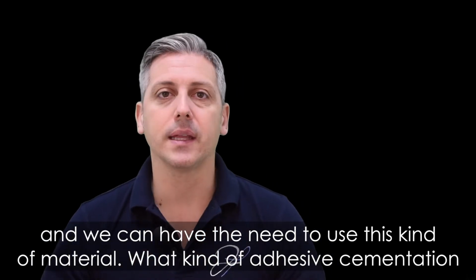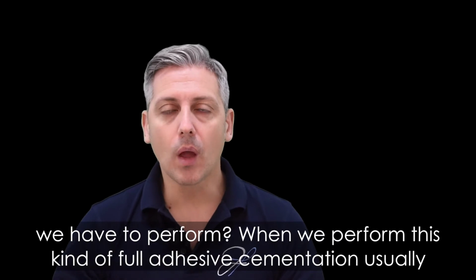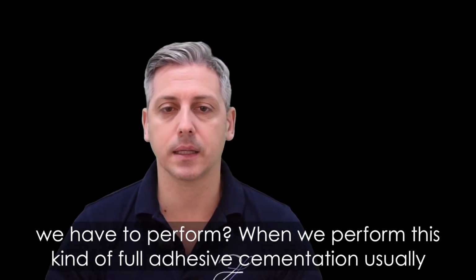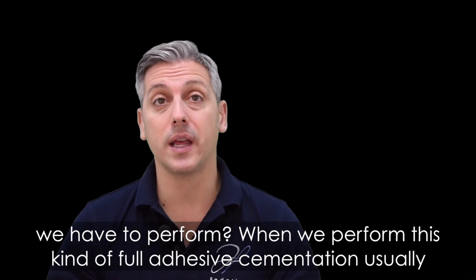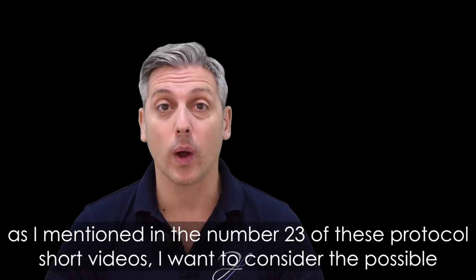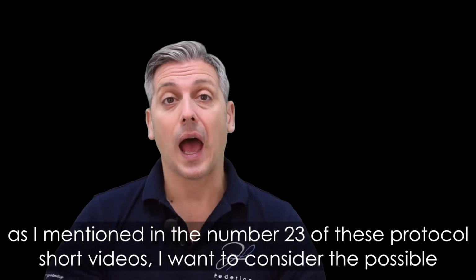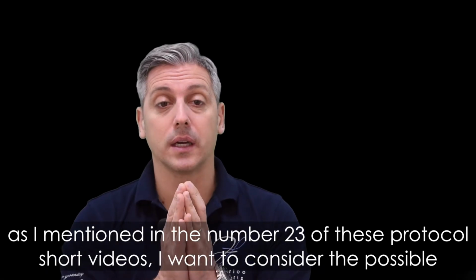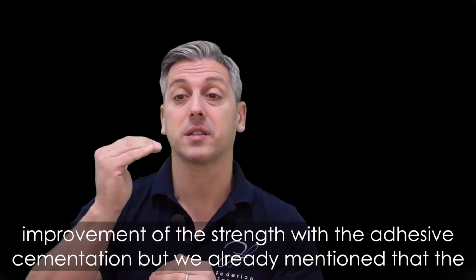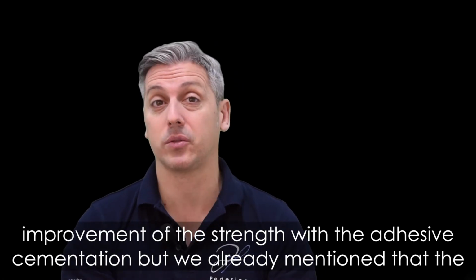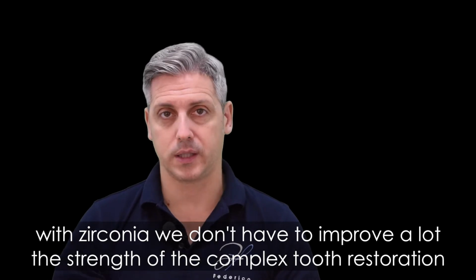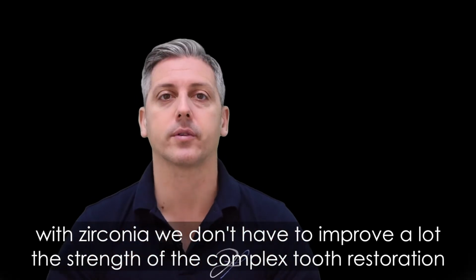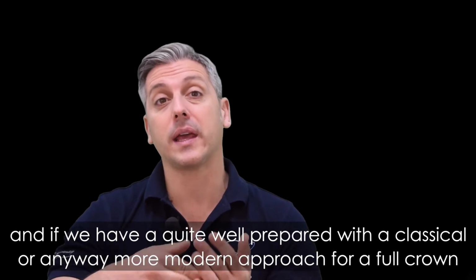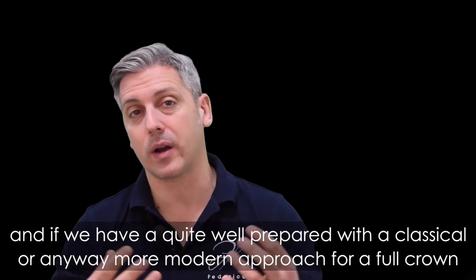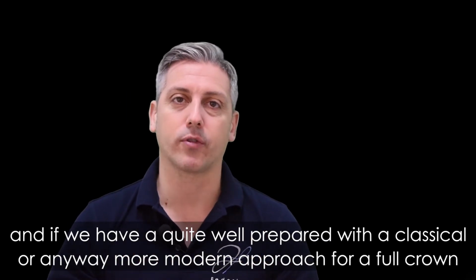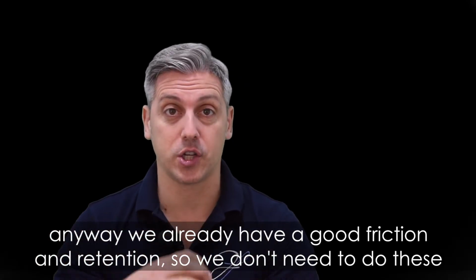Well, what kind of adhesive cementation do we have to perform? When we perform this kind of full adhesive cementation, usually, as I mentioned in number 23 of these protocol short videos, I want to consider the possible improvement of the strength with adhesive cementation. But we already mentioned that with zirconia, we don't have to improve the strength of the complex tooth restoration a lot. And if we have a well prepared tooth with a classical or more modern approach for a full crown, we already have good friction and retention.